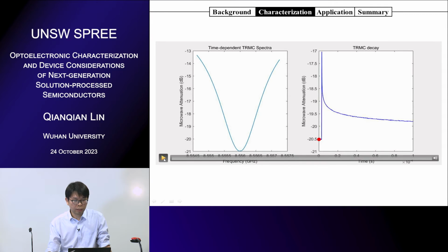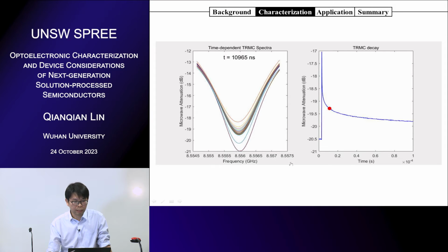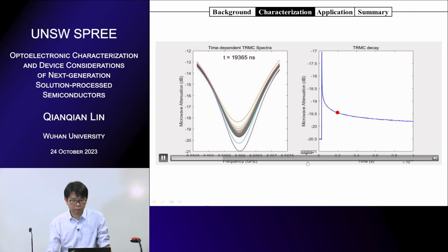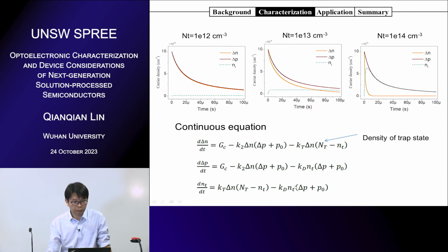This is a typical TRMC measurement we recorded in our lab. So we can record the spectra versus time, and we can get the amplitude versus time as well. So from this time-resolved measurement, we can analyze the mobility and carrier recombination processes. And we can also fit the decays under different intensities. If you have different decays, you can fit with the continuum equations, and you can easily get the density of trap states. So this is a fitting of the decays.